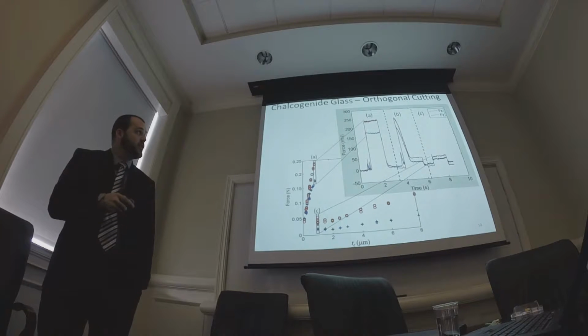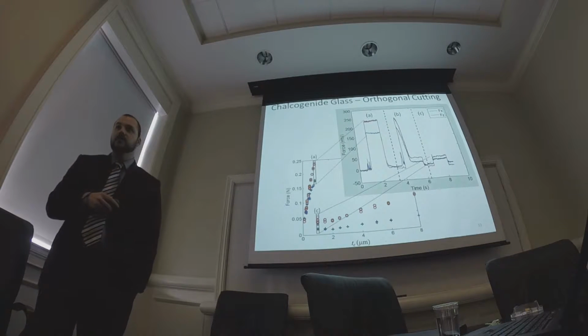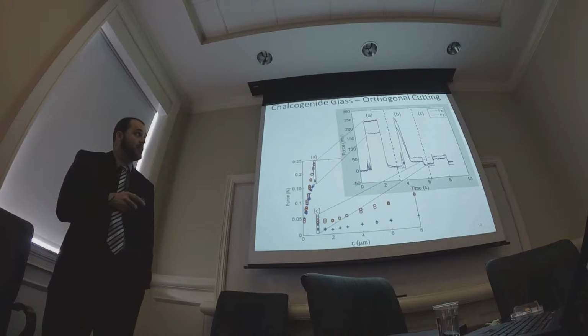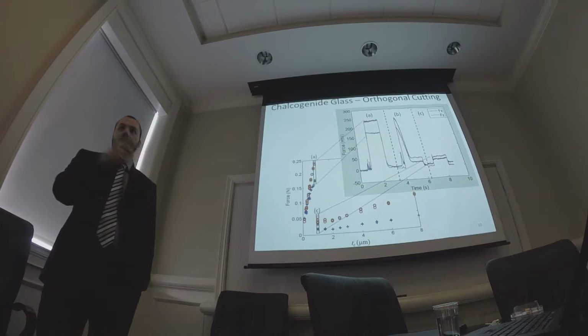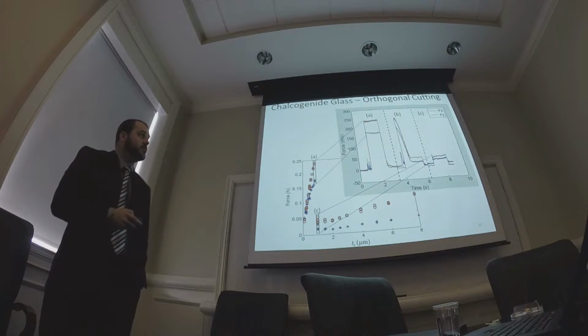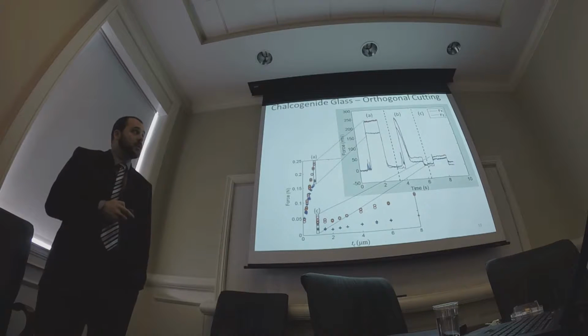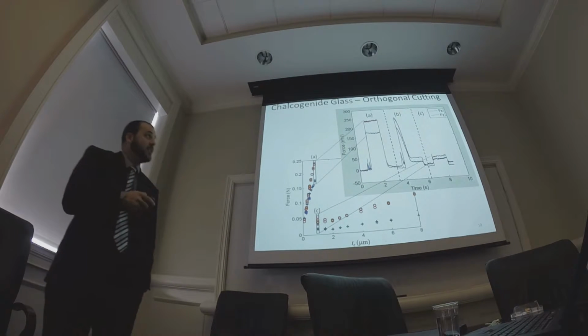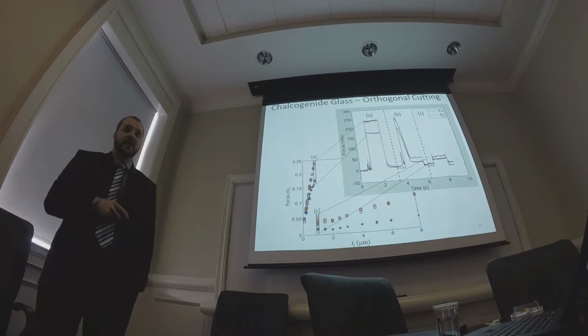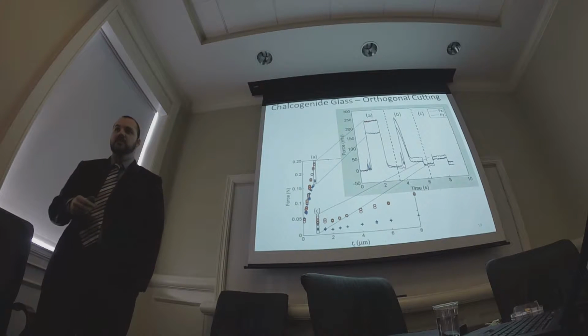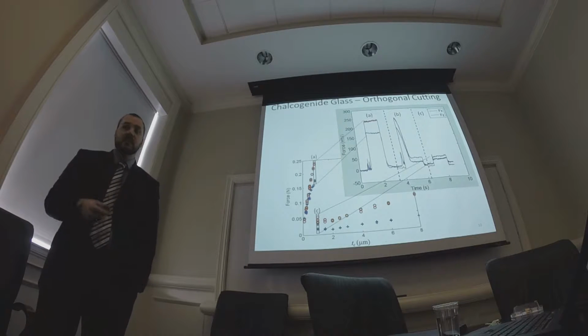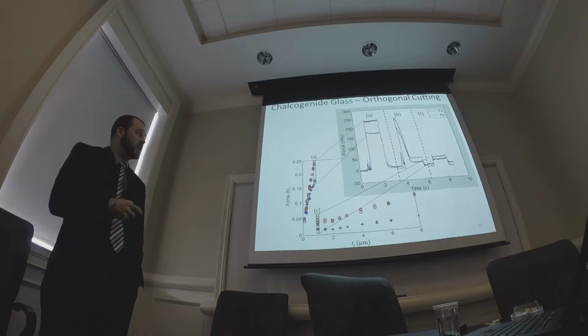Yeah, so this test from here to here is 80 revolutions of data. So this is happening over full cycles of cutting. It happens quick, but it's still about 30 revolutions of data to get. And this transition - it wasn't always 30 revolutions of data to get to steady state. This varied based on how big of a jump we made.